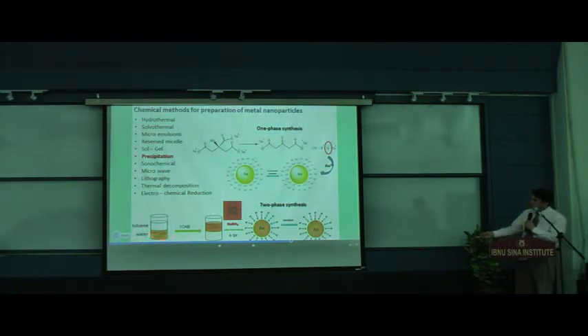You put gold precursor in water. With the help of a phase transfer agent, you can transfer the gold ions into the toluene. And here, this is the key point: chemistry of gold and sulfur in the presence of a reducing agent. But our interest is these R groups. They can be anything. You can put anything you want. You just need some synthetic hand to produce this molecule for you. Then with the help of this chemistry, you can put it here and go on.